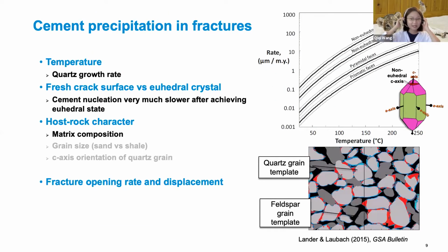So now we've trained our eyes on seeing the internal structure of a natural fracture and how it looks. This slide presents a study by Lander and Laubach. They listed several factors that affect cement precipitation in fractures. Those factors can help infer, under certain thermal conditions, whether we expect to see just a thin layer of cement lining the fracture, or cement growing as bridges but still leaving a lot of pore space, or maybe a fully filled fracture, which would not be conductive. Let's start with the first factor, the temperature. It governs the quartz growth rate. The higher the temperature, the faster the quartz cementation growth rate, right?